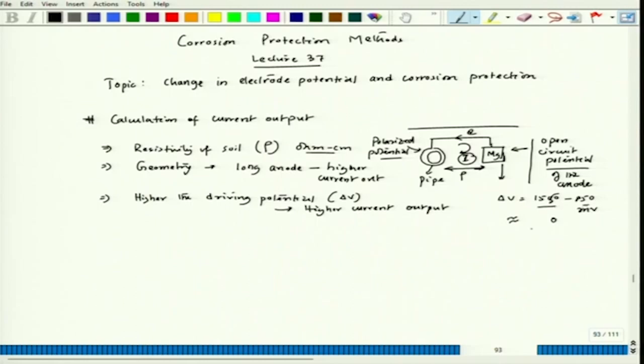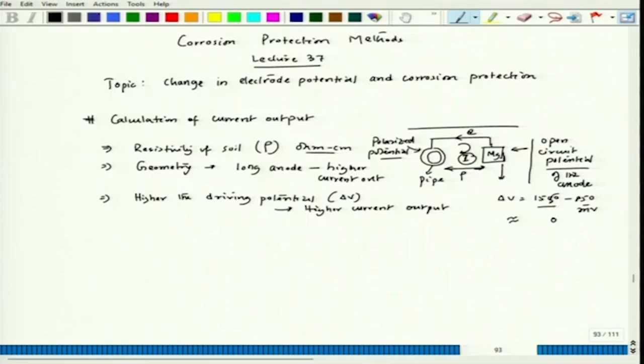So, these potentials in case of cathodic protection, generally a copper-copper sulfate reference electrode is used for measurement of potential, because this reference electrode is very rugged and it can be carried by hand. And it doesn't break easily. At the same time, when we try to measure soil resistivity or the polarized potential of the sacrificial anode or the pipeline, what we have to do is connect the terminal between the pipe and that particular copper-copper sulfate reference electrode.